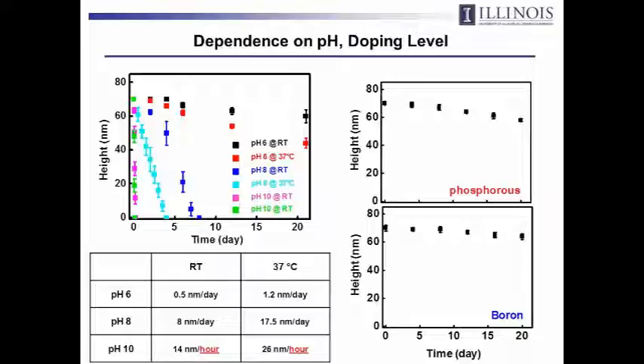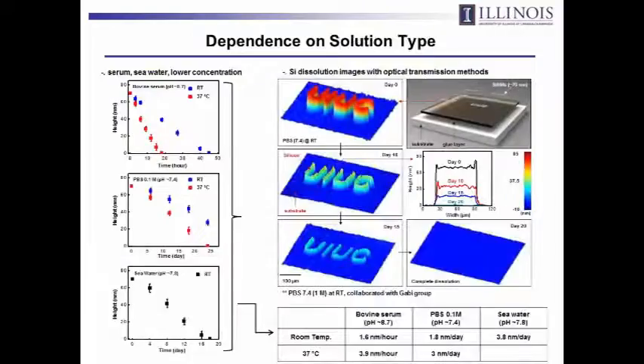And so for the dissolution, you have to think about where it's being placed in the body, whether it's going to dissolve given the pH conditions, and likewise in the environment. But at least in a range that's reasonable here, it will dissolve, although it goes away very slowly. It depends, though, on doping level. If you add phosphorus or boron, then the rates decrease substantially, but they're still non-zero. So given a long enough time, they begin to disappear.